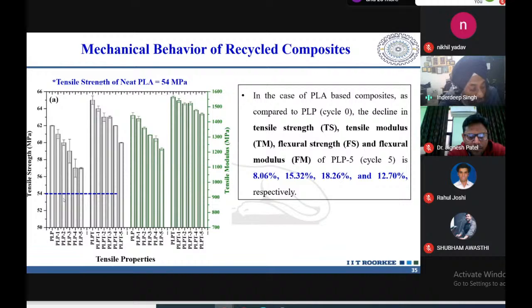So which means that for any product that is made up of only polymer, if we put fibers into that polymer at the fabrication stage, that fiber will not only improve the mechanical properties of that polymer, but also help in the recycling aspects. We conclude from here that the number of cycles it can be recycled may vary with the fiber and polymer combination, but for this case study we have seen that even after 5 recycling steps, the material can still be reused for certain applications.